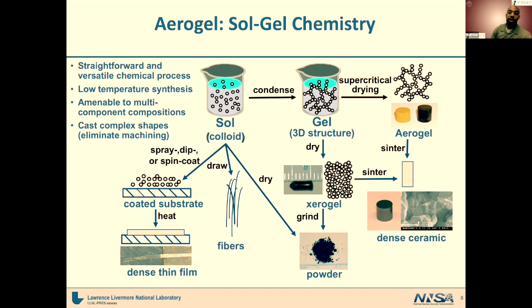And then if you simply drop the pressure while maintaining the temperature, you can move from a supercritical fluid to a gas. So it's a way to basically go from having a liquid within the pores of your gel, to the supercritical fluid, and then to a gas, which, as you release the pressure, you are basically just letting go, and you're able to avoid the capillary pressure that typically would happen if you were just to directly evaporate the liquid. And so when you do that, you are essentially replacing this liquid with gas, so you don't get capillary pressure, no collapse of your pores, and you're able to maintain that 3D structure in your aerogel. And so this is the typical way in which these aerogels are made.